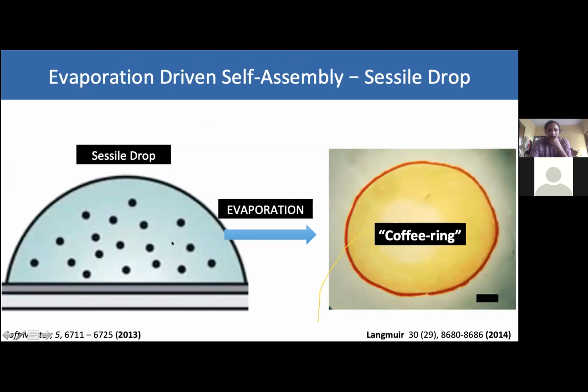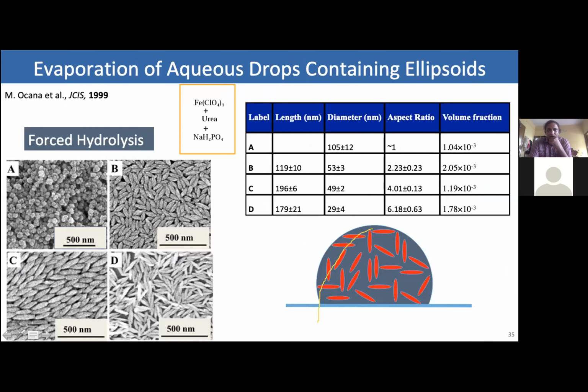One thing to keep in mind is that the evaporation of sessile drops gives coffee ring deposits, and with this background, we look at drops that contain several types of particles, that is, particles of different aspect ratios. We've been able to make particles that have different aspect ratios: almost spherical, what you see in A, and B, C, D show elliptical particles of different aspect ratio. One thing to notice is that these particles are very, very small. The length of the particle is about 100 to 200 nanometers, and the diameter varies from about 29 nanometers to about 105, and the ratio of the length to diameter gives you the aspect ratio, which varies from about 1 to 6.